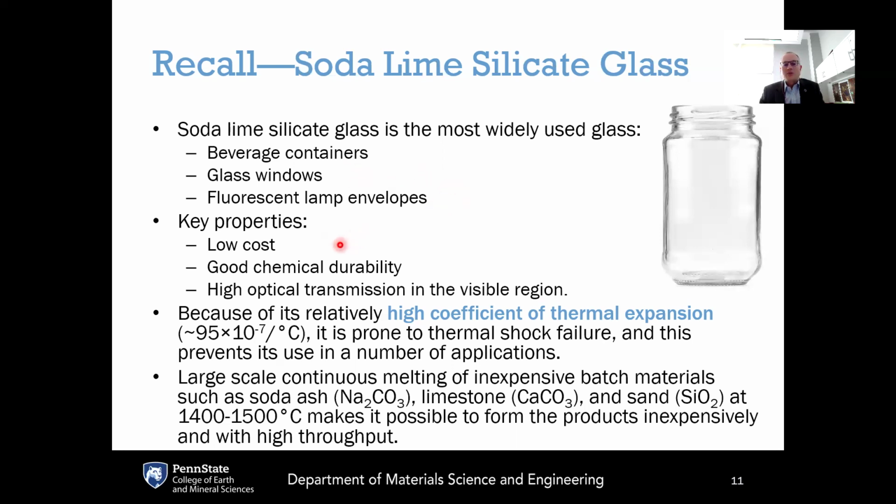And some of the key properties are its low cost. It's made from very cheap batch materials, quartz sand, soda ash, limestone. Its chemical durability is not as good as fused silica, but it's good enough for most applications. It's good enough for most beverages, for food packaging. And the transparency is not nearly as good as fused silica, but it's good enough for everyday items like windows, where you only need transparency through the thickness of the glass.